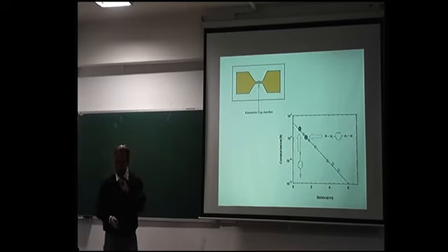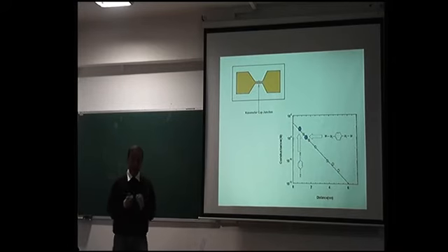Okay, so now you plot the conductance versus distance, from the tunneling current. You can do that, and you will see that when the gap is in this region, it exactly matches the width of the molecule. That means if I get a conductance of this value, that is an indirect hint. Because in the FESEM you cannot see anything below 5 nanometer, but typically a molecule is 1 to 2 nanometer.